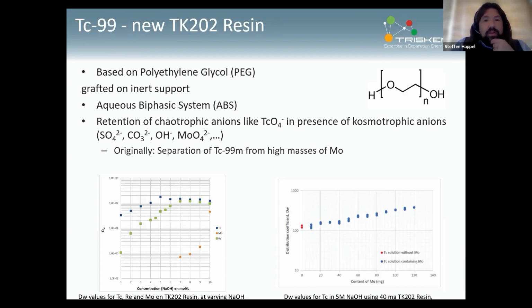So basically what you need to extract ions like pertechnetate or perrhenate is a fairly high concentration of water structuring anions: sulfate, carbonate, hydroxide, molybdate. That's also the original application. Originally, we've been working on that mostly for the separation of Tc-99m from irradiated molybdenum targets, fairly large, up to a couple of hundred grams. So the presence of a large amount of anions of matrix in that special case is actually quite beneficial.